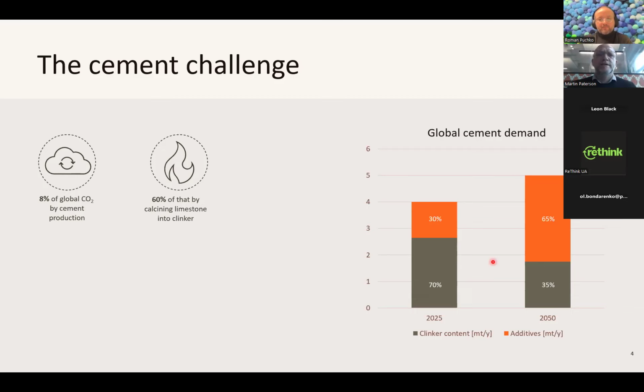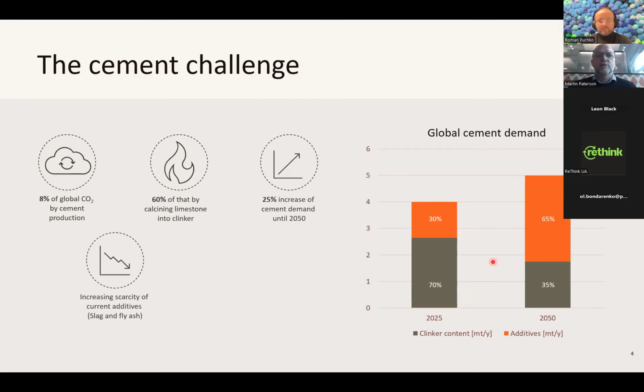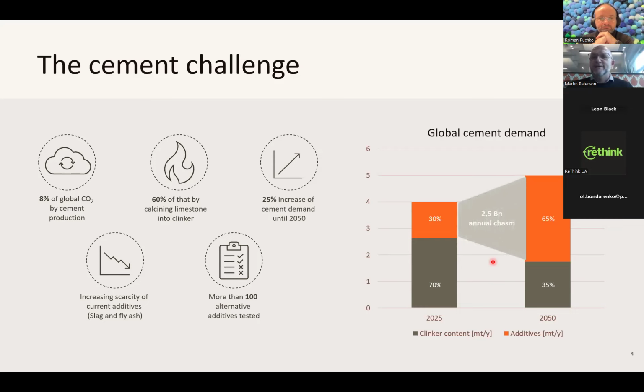I think Leon also alluded to it: 60% of the emission comes from calcining the limestone. We have an increase in cement consumption. The current additives we're using, which are mainly slag and fly ash at the moment, are getting scarce. Fly ash is a byproduct from coal-fired power plants, and we're using them less and less. Slag comes from producing steel, and there also the production process changes, going away from furnace production more to hydrogen, which also makes slag less and less available. So the industry is really looking for alternatives. One thing is, of course, the scarcity of the current additives, but then also if you look at this chasm from now until 2050, we're looking at roughly 2.5 billion tons of SCMs which we need per year.